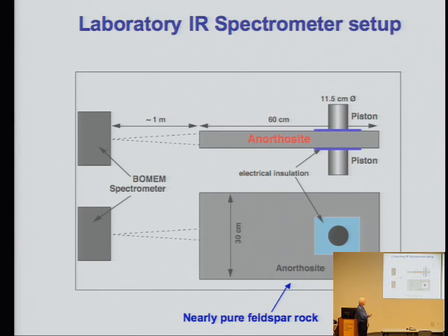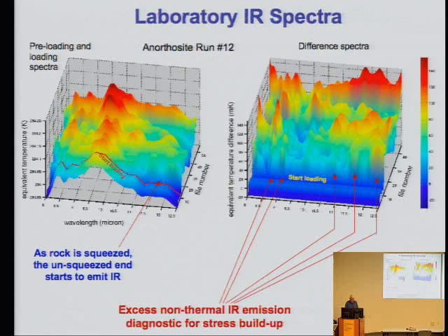For 6 minutes, we recorded the baseline, and then we started to squeeze until the rock broke, which took about 36 minutes, so we didn't go very fast. We slowly increased. On the left, you see the actual spectra, from 8 micron to 12.5 micron, up to this line which says start loading. This is the time axis, this is the intensity, and the experiment was ended by the rock breaking.